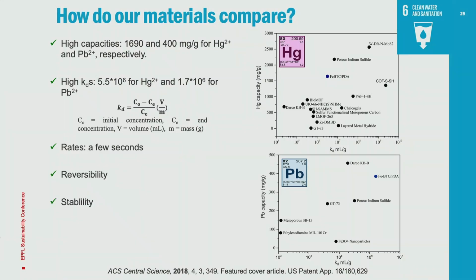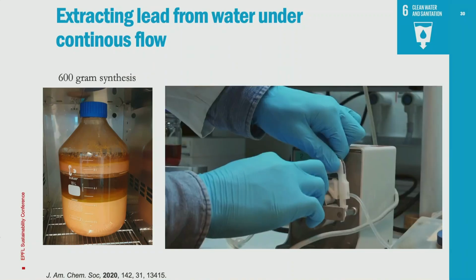Then, I told you it was reversible. It's highly stable. We soak it in water for extended periods of time. We don't see any leaching of our components. And interestingly enough, it also resists clogging from various organics, which is a common problem. And we believe that the reason this happens is because our pore sizes are actually so small that it inhibits these molecules from going inside and blocking the pores of the material. Okay? So now we're scaling the materials up.